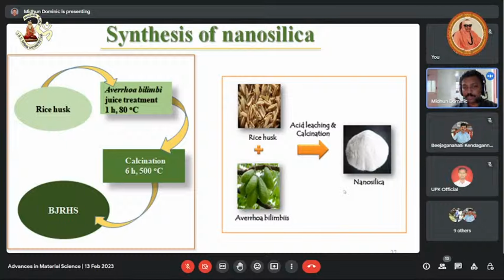Here we adopted a green and simple one-step synthesis for the preparation of nanosilica by using Averrhoa bilimbi fruit juice. In Malayalam, it is called pulli. I don't know what it is called in Kannada. So this is the Averrhoa bilimbi fruit. Instead of burning rice husk directly in a muffle furnace, first we treat the rice husk with Averrhoa bilimbi fruit juice for 1 hour, and the juice is washed away from the rice husk. Then this treated rice husk is calcined in a muffle furnace at 500 degrees Celsius for 6 hours, and we get pure nanosilica.